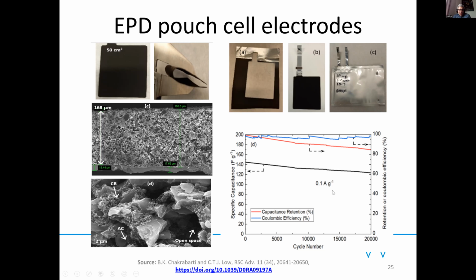And here we show some cross-sectional SEM images, a FIB-SEM image, to show the thickness of the electrode. The reason we are showing this here is because normally, if you look at the literature for electrophoretic deposition for supercapacitors or lithium-ion batteries, the electrodes are very thin. They're not as thick, and they give reasonable performance because of the good utilization of the electrolyte within the electrode space at thin layers.